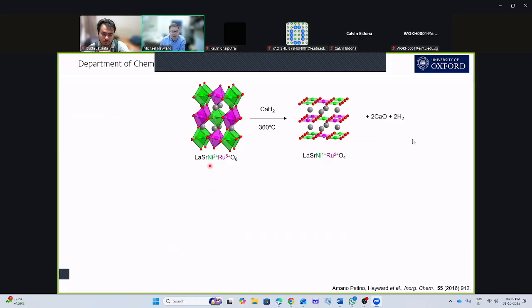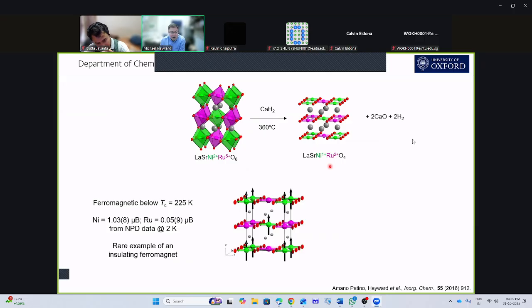Now we've got nickel and ruthenium as our transition metals, which adopt an ordered structure. And if I treat this with calcium hydride at 360 degrees C, I can make this compound, which has square planar nickel 1+ and ruthenium 2+ in its framework. And this material is quite interesting because it adopts a ferromagnetic state, a magnetically ordered state below 225 Kelvin. And it's a rather unusual example of a ferromagnet that's also insulating.